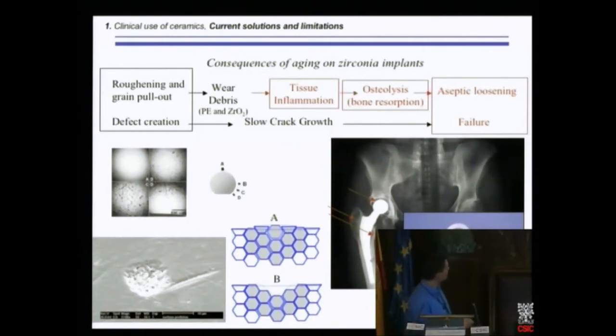What you see is that you have some craters at the surface of the zirconia implant. This is due to the fact that this transformed zone has been pulled out, and you have a lot of pull-out, and this crater means transformation and grain pull-out. So the consequences of aging are clearly roughening and grain pull-out. This means wear debris, and remember what we said in the first presentation. Wear debris means tissue inflammation, bone resorption, and then aseptic loosening, and the need to change the hip component.